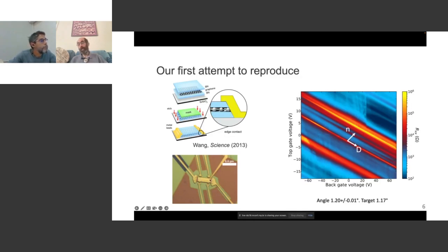It turns out we have an electrode on the top and one on the bottom. And so if you change those voltages in opposite directions, you stay on one of these similar colored lines. That's where the density of electrons in the graphene, the twisted bilayer graphene, is remaining the same, but you're changing the electric field normal to the plane, the so-called displacement field. But if you go in a different direction, you're changing the density of electrons in this twisted bilayer graphene without changing the electric field normal to the plane. Some features that you may notice are this feature at the so-called charge neutrality point. That's where you have zero extra electrons in the twisted bilayer graphene.